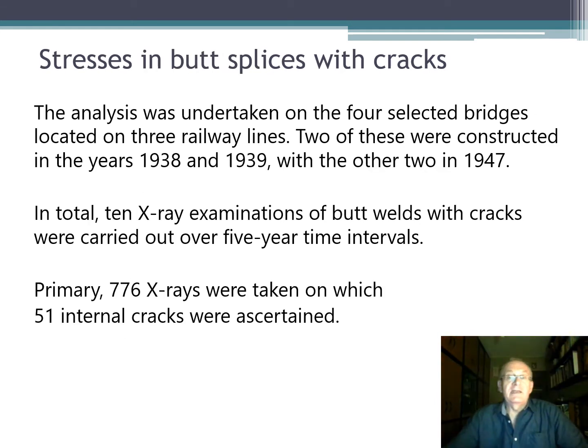An analysis was undertaken on four selected bridges located on three railway lines. Two of these bridges were constructed in the years 1938-1939, with the other two in 1947. So it was the period when the quality of butt welds was not so good. In total, 10 X-ray examinations of butt welds with cracks were carried out over 5-year time intervals. Primarily, 776 X-rays were taken, on which 51 internal cracks were assessed.